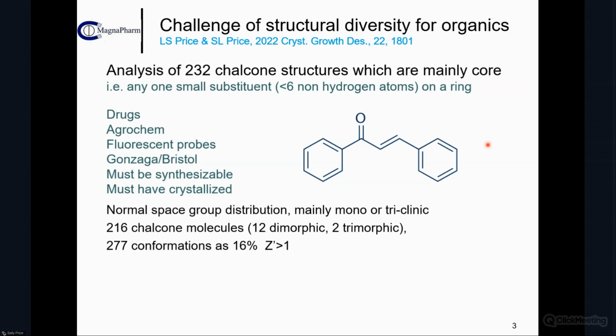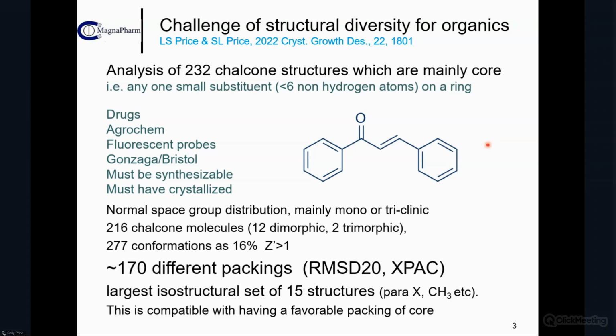So we did an analysis, and to our surprise, 232 crystal structures generated 170 different packings, either on the basis of being able to overlay a 20 molecule cluster, ignoring molecular differences, or from the XPAC analysis, which is more dealing with the long range order form. And this was because the largest, by far, set of isostructural crystals only contained 15, mainly parasubstituted halogens and methyls.